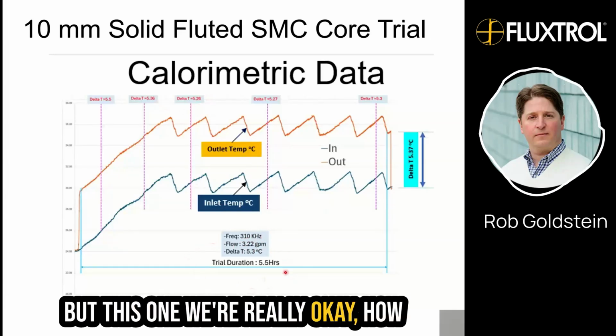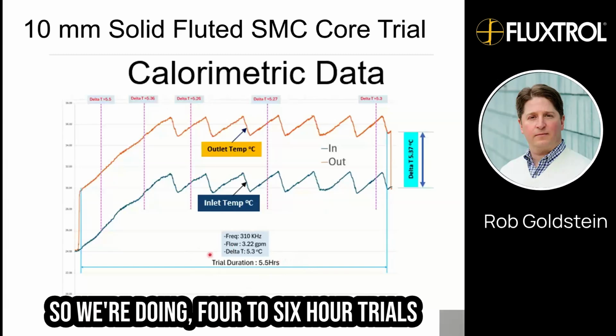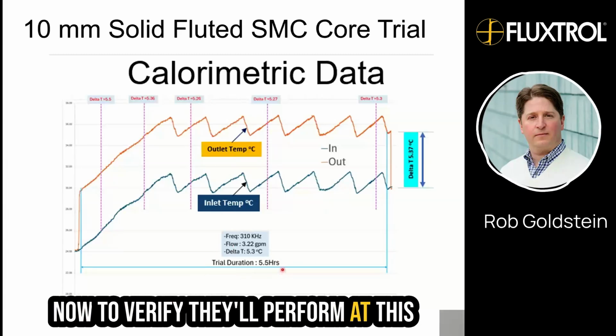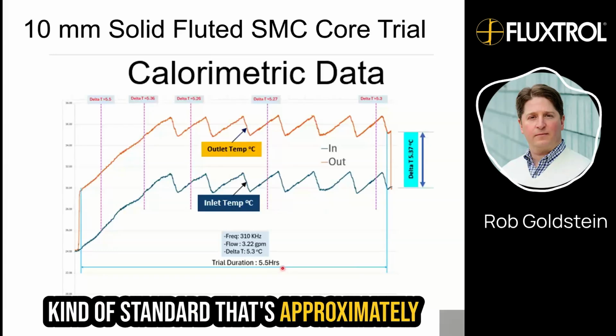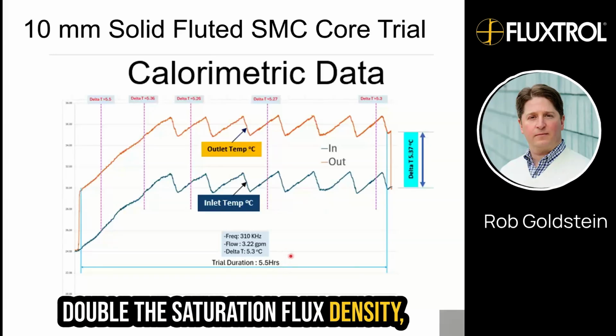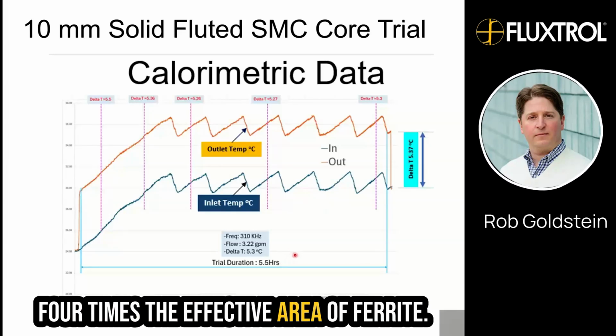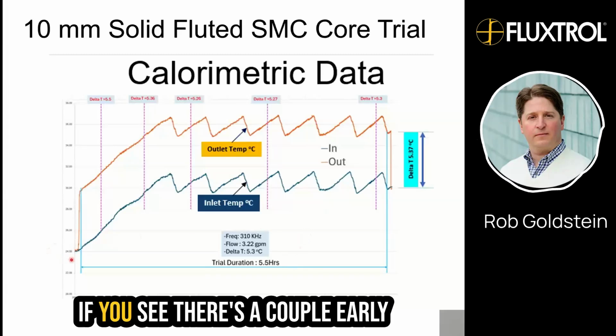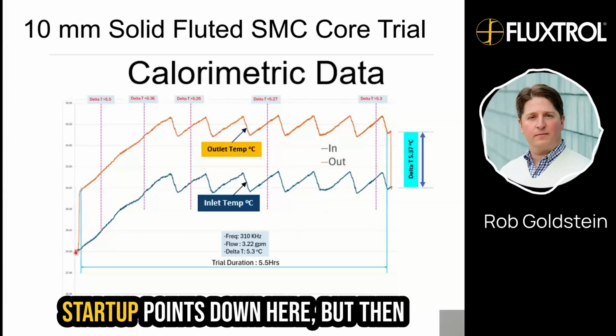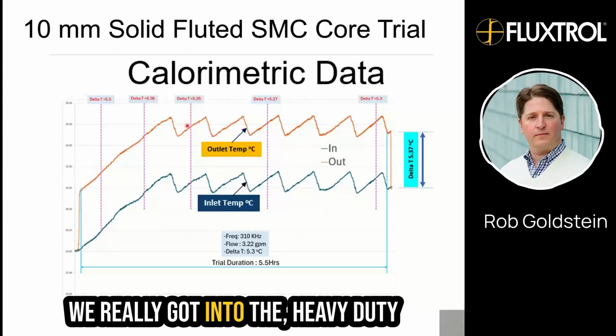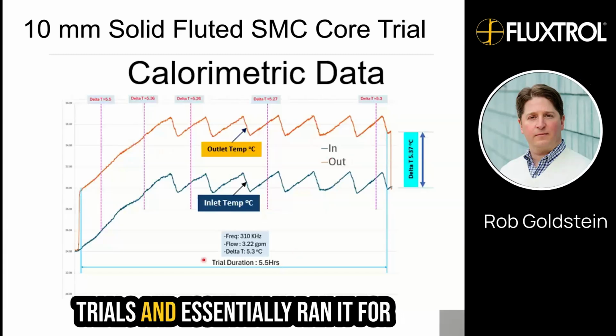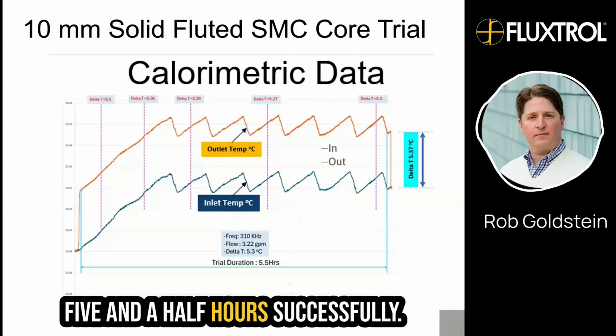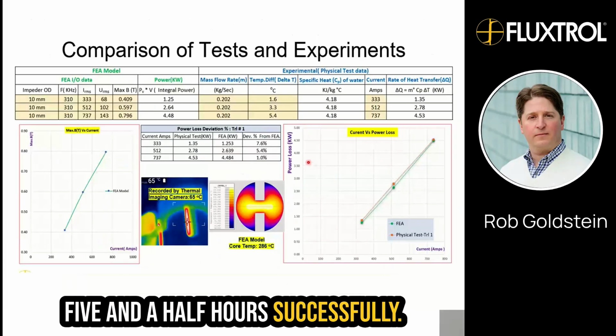But this one we're really asking, okay, how long will these survive in the field? So we're doing 4 to 6 hour trials now to verify they'll perform at this kind of standard that's approximately double the saturation flux density, 4 times the effective area of ferrite. If you see, there's a couple early startup points down here, but then we really got into the heavy duty trials and essentially ran it for 5.5 hours successfully.